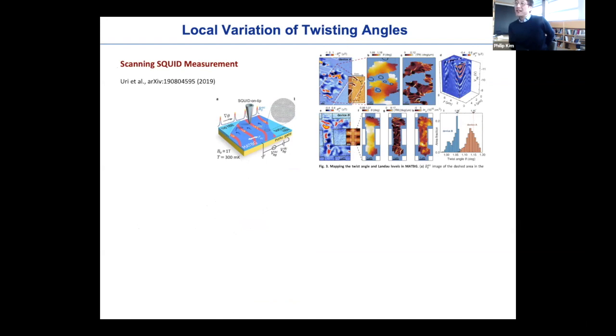Well, it turns out that's probably not the case as you expected, and there is always disorder, including a certain angle distribution. This is a paper done by Eli Zeldov's group using a scanning SQUID. They imaged the angle distribution of this close-to-magic-angle twisted bilayer sample provided by the MIT group. And they see that, yes, on average it is close to the magic angle, but there's a substantial distribution of the angle, depending on the sample. This will tend to create, especially when you get into the superconducting regime, some percolation pathways of superconductors throughout the sample. And when the percolation is made, then between the voltage probes you can read out the superconductivity.